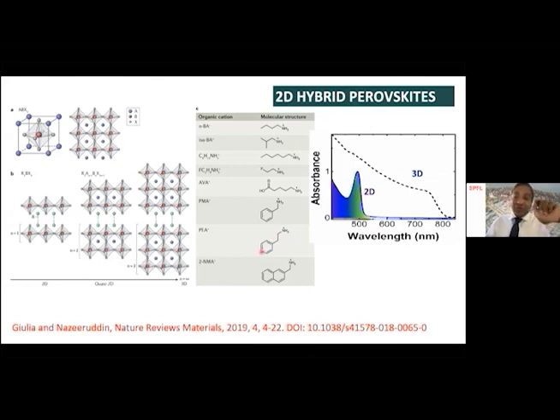Then you can ask why we are doing this fluorine substitution. Perovskite composition has iodides, and if you look at the basic chemistry, there will be halogen bonds. The interaction between the iodide and fluorine can be enhanced. This way, when we deposit this two-dimensional perovskite on top of three-dimensional perovskite, we want to create an interaction between the two layers. That you will see in the presentation.